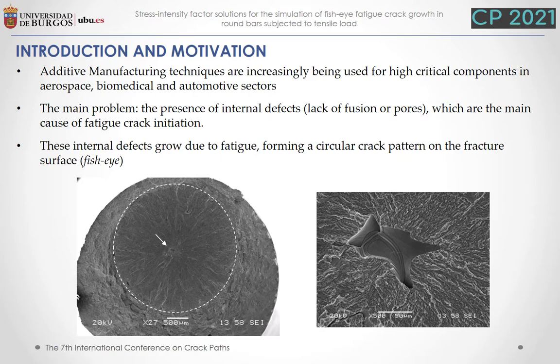Additive manufacturing techniques are increasingly being used for highly critical components in aerospace, biomedical, and automotive sectors. The main problem with these techniques is the presence of internal defects, like fusion defects or pores, which are the main cause of fatigue crack initiation. These internal defects grow due to fatigue, forming a circular crack pattern on the fracture surface known as a fisheye.